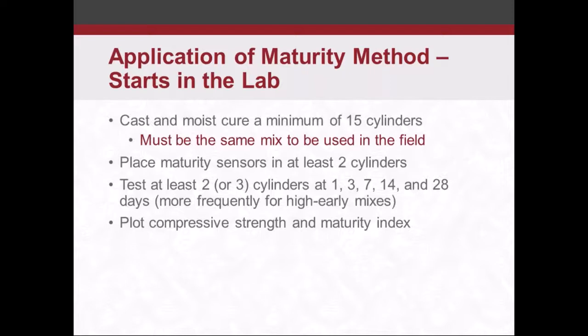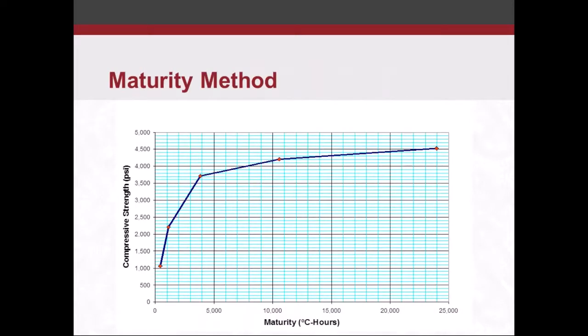And then we test a couple of cylinders at different ages: 1, 3, 7, 14, 28 days. Maybe we're testing them more frequently for a high early mix, or even more frequently, depending on when you want to load them. And then you plot the compressive strength against the maturity index, and you get something that looks like this. Again, down here on the x-axis, the maturity is simply the temperature multiplied by the time. And then each time we break a cylinder, we figure out what that maturity value is, and then we plot the compressive strength. So as it ages, our compressive strength goes up, gets to a certain point, and that reaction rate, that strength development, starts to slow down.